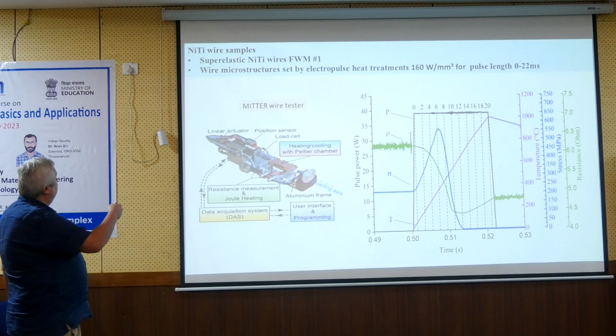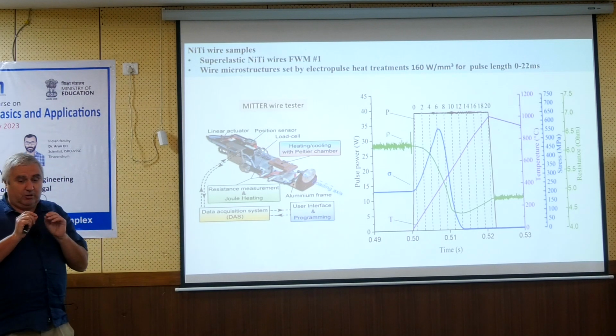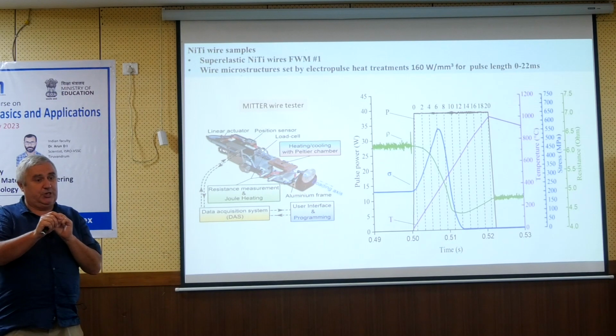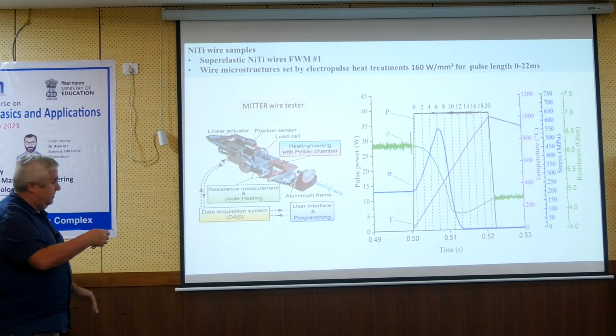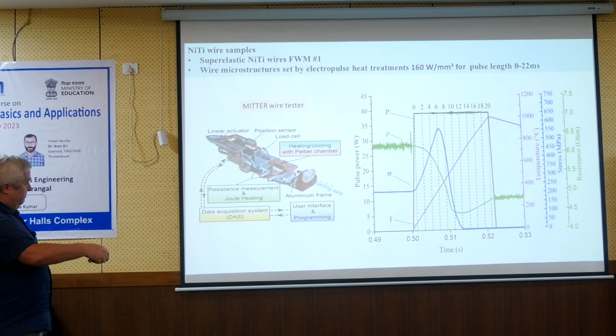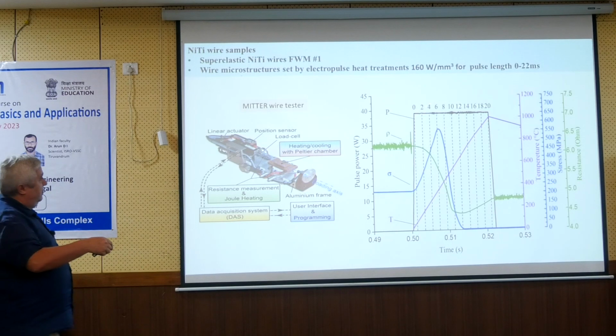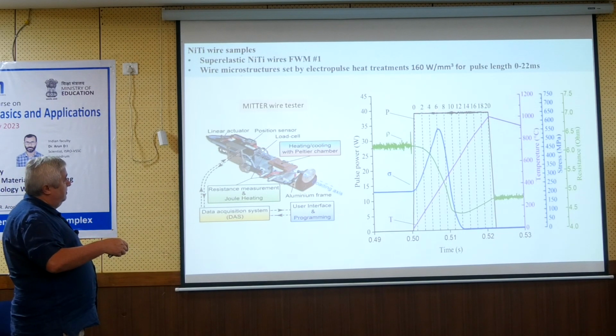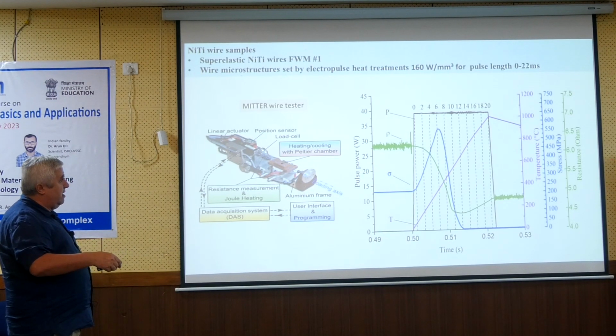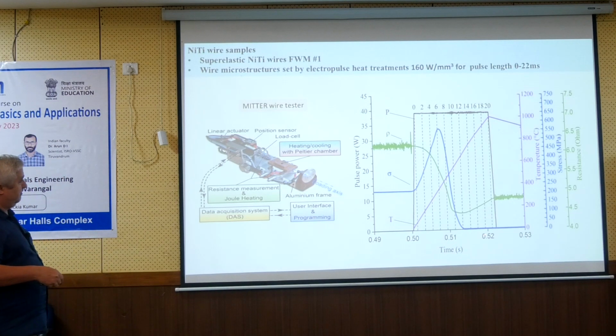So we have developed this electro-pulse treatment, where we send a short electric power pulse into the wire. The temperature is not 500, but maybe 700, but only for a very short time. Here is the estimation of the temperature when we send this power pulse. Of course, this is the time for 8, 10, 20 milliseconds. If we continue, the temperature will increase and the wire will break. But when we stop at 20 milliseconds, the temperature goes down. Still, it is exposed to high temperature for some time, but the time is in milliseconds.